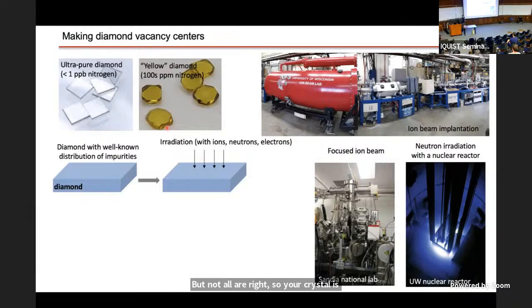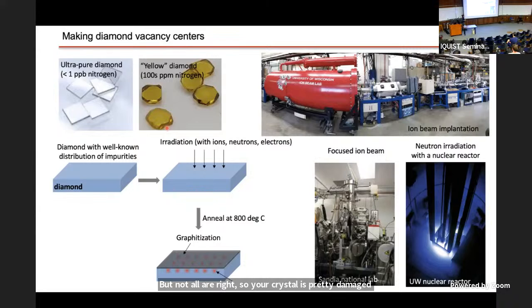So what we do is we heat up the crystal through this annealing process, and that mobilizes the vacancy. So the crystal is healing itself, and then the vacancy can also find a nitrogen. And when that happens, you have a good chance of getting an NV center. After annealing your crystal for some time, you get a certain amount of graphitization on the surface that you then clean up with chemicals, with acids in particular.